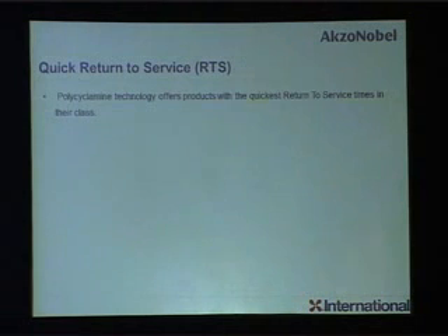So in the interest of time, I'll just go to the highlights. If you go for polycyclamine cured technology with epoxy novolac, it will have superior chemical resistance. It will have high temperature resistance up to 120 degrees centigrade. It can be applied up to 1 mm, even 2 mm thickness. There are a lot of examples where, in exterior applications, instead of conventional technology, people are going for this type of coating because it gives you a monolithic film. There will be a uniform film, with no chance of any joints and all those things. Then ultra high solid technology, zero VOC, no pollution and hazards. And another important advantage is a very quick return to service. If you apply this, within 4 hours you can ship your painted structures. You don't have to wait for days.